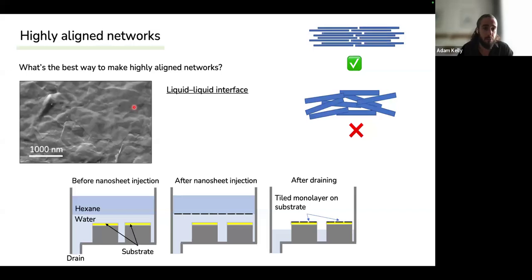So it's very, very wasteful. Another way to do this, what we've developed, is using a liquid-liquid interface. So you take something like water and hexane, which have very different surface energies, and then you inject your nanosheets into the interface between these two solvents. And then these nanosheets will form a network along the interface. And if you do something then like pump out the solvents, you can deposit this network onto a substrate.